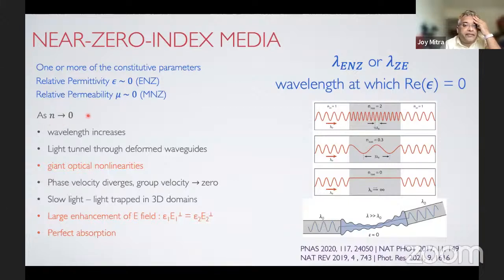And if the refractive index of a material does go to zero, then what happens? The wavelength increases. Light can tunnel through deformed waveguides, and you can see a cartoon here from one of the review articles. I have listed quite a few of the review articles which have come out in recent times, and they are all very good, highly recommended. So as the refractive index goes to zero, you can see the wavelength stretches itself. Light can tunnel through deformed waveguides. There have been reports of giant optical nonlinearities. You can very easily show that the phase velocity diverges, whereas the group velocity practically goes to zero, bringing us to slow light, or light trapped in 3D domains, small but finite domains.